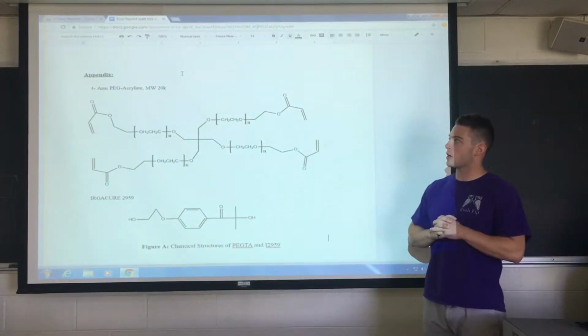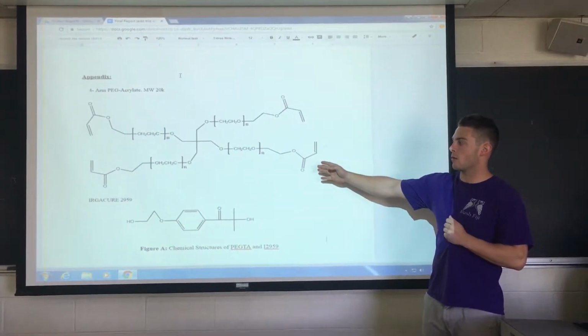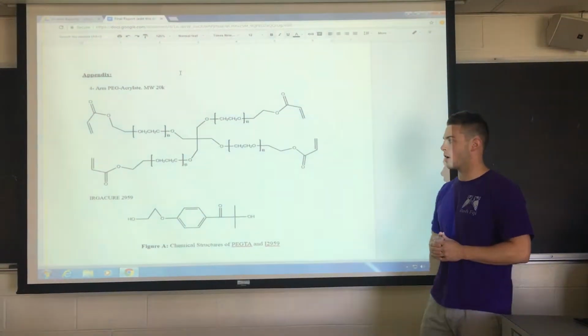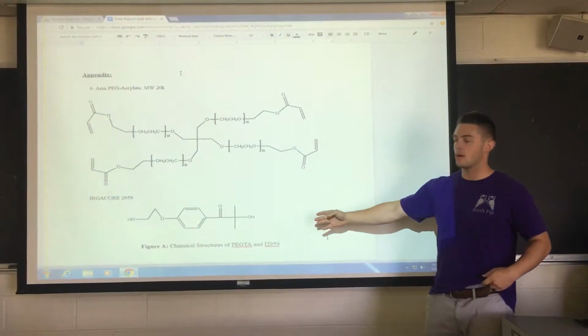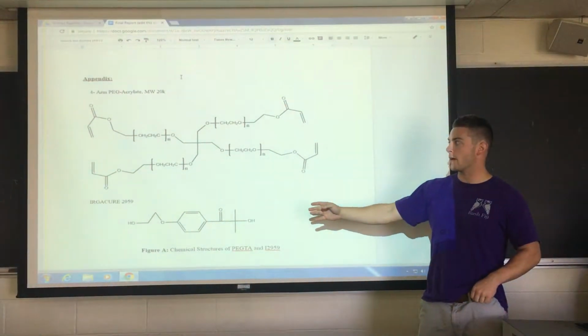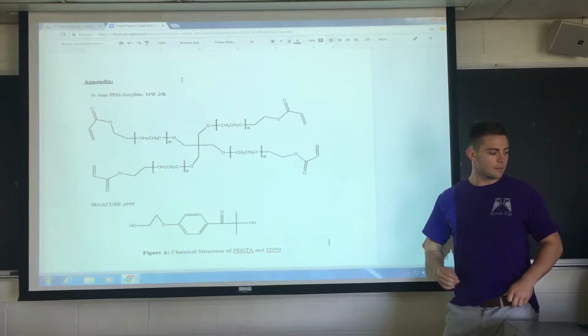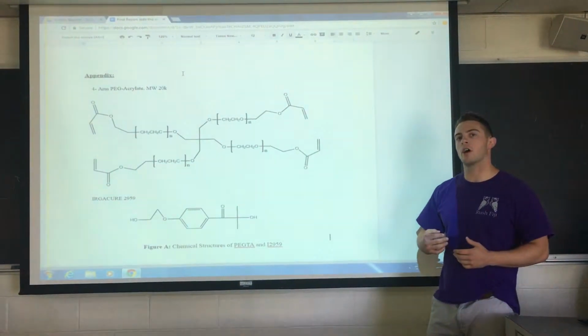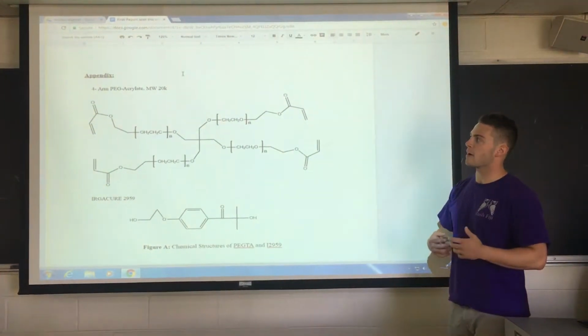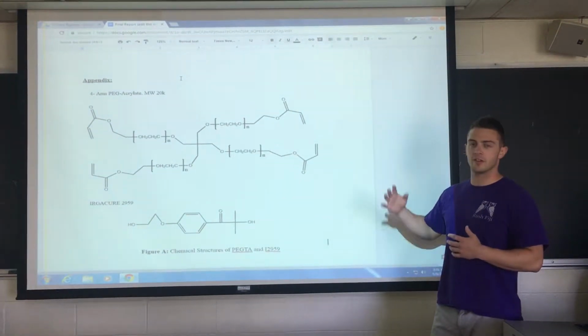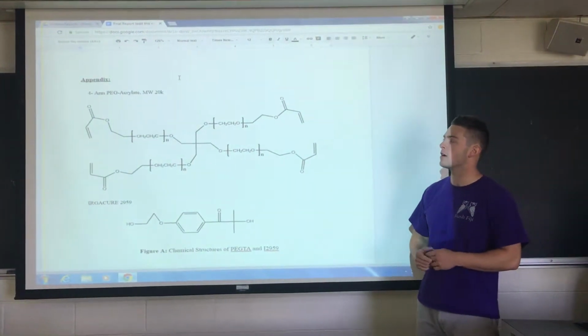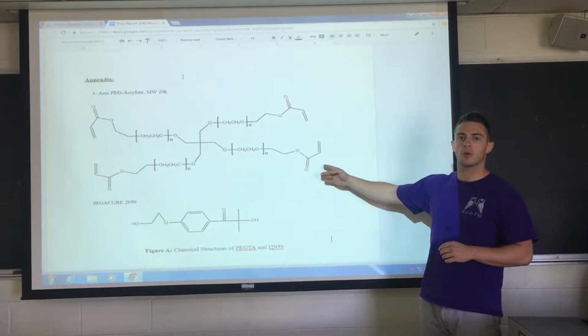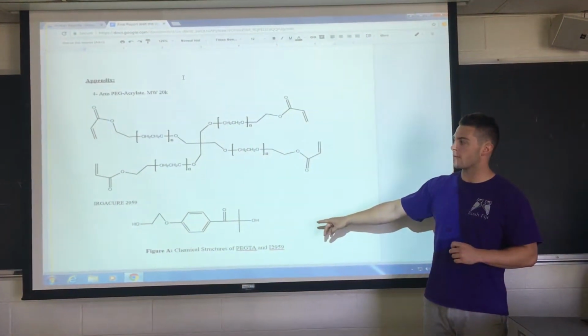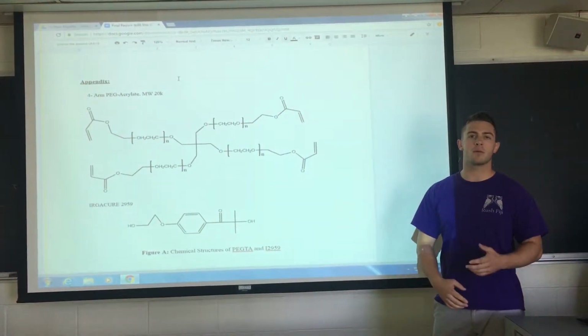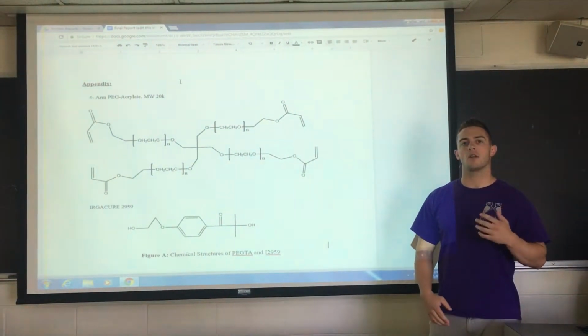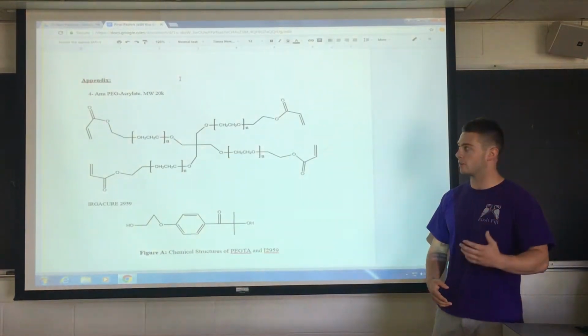So after we selected our polymer, the 4-arm PEG acrylate, we also had to look into a photo initiator, and we selected Irgacure 2959 because it's water soluble and is often used with PEG. Some degree of cross-linking tests were conducted, and we optimized the formulations of this mixture so that we had 2 different combinations of 15% and 20% PEG and 0.05% Irgacure, as well as 5% gelatin. And the gelatin's in there so that the material is viscous enough so that it can print.